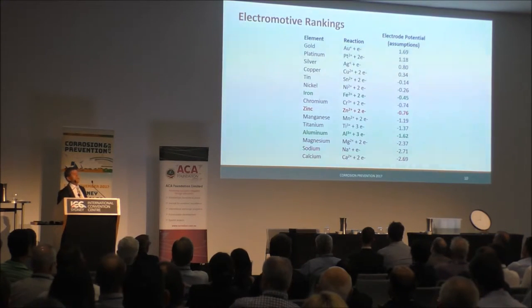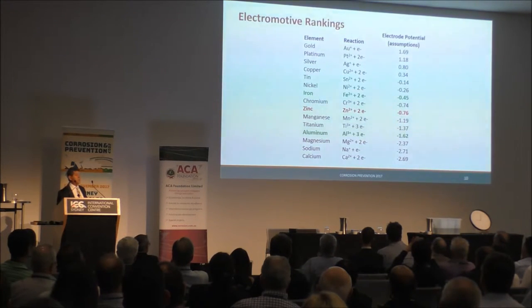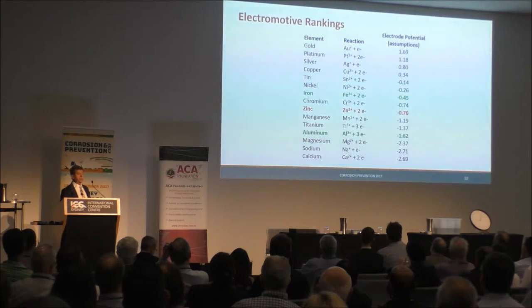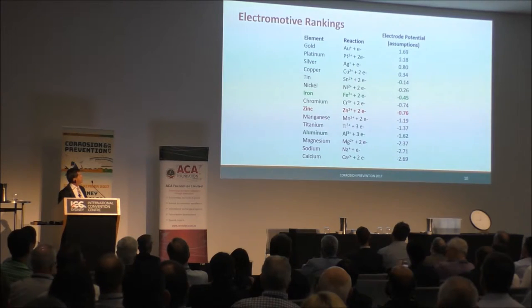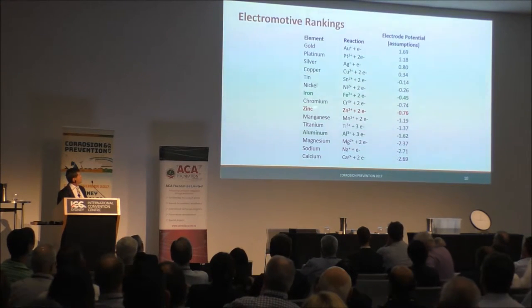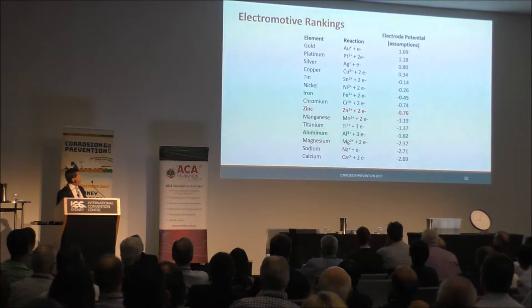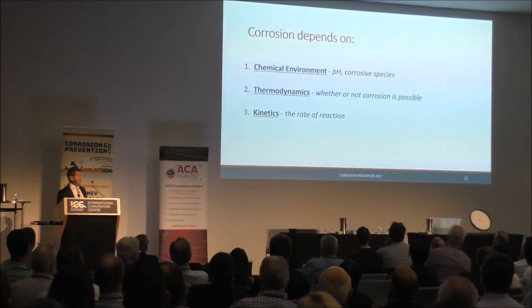In terms of many applications that we have, including iron and steel, we can see that that driving force and the electro-potential difference between iron and zinc is significant enough that we can use zinc to react and corrode preferentially to iron and steel, so that it can be used as a galvanic protection metal to help protect irons and steels. But of course, you can't use zinc for aluminum, because the aluminum is much more reactive than zinc. So we take into account all of these factors when we're thinking about paint.